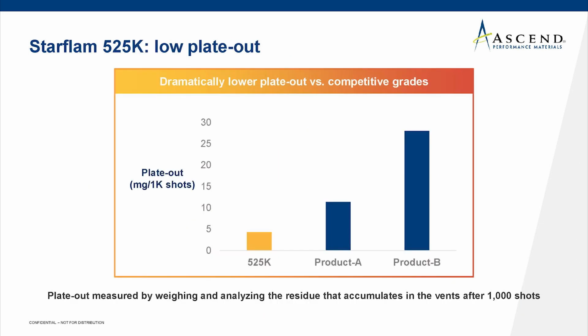Another aspect that molders care about is plate out. And this relates to how much residue can get stuck in the vent lines. Basically what we do is we weigh the amount of material that's caught into the vent lines, and we dissolve it in methanol and then evaporate it and measure how much material was accumulated. And this is done over 1,000 shots. And we can see that our 525 grade exhibits much lower plate out versus competitor products A and B.